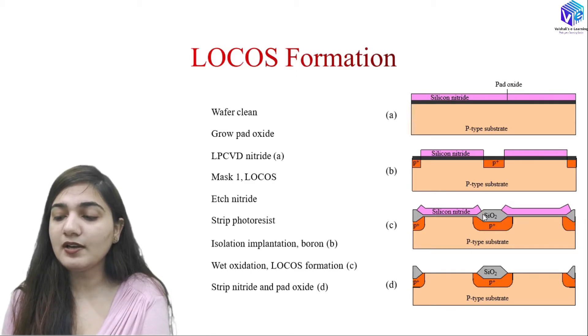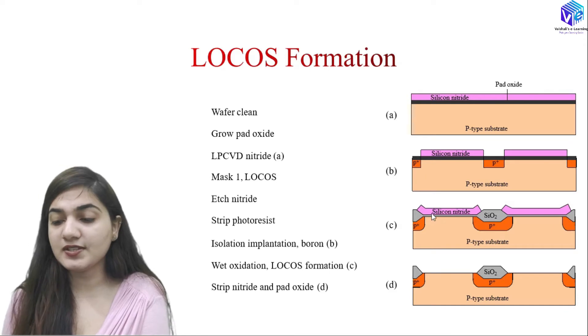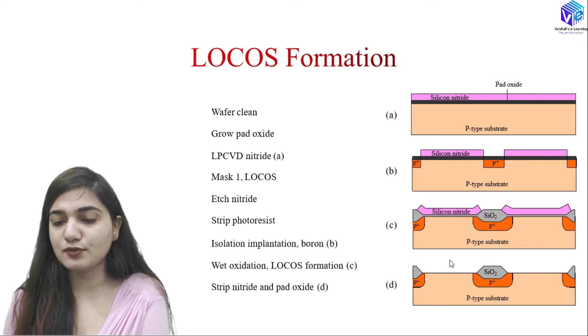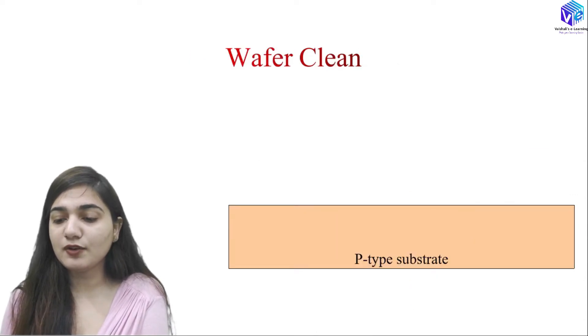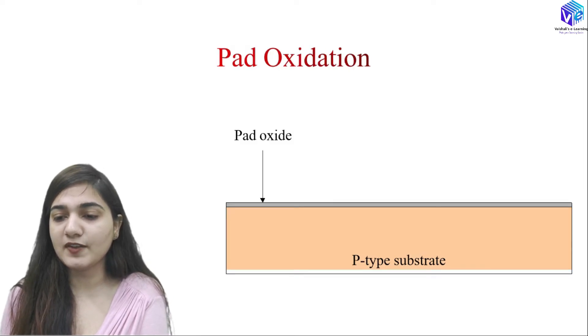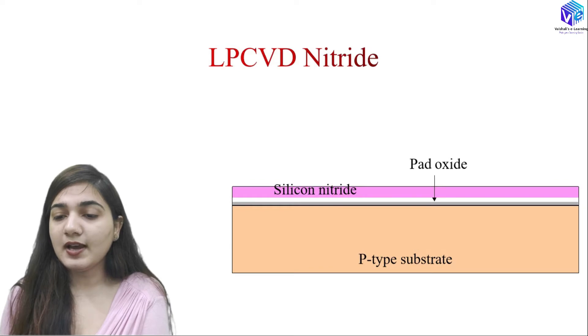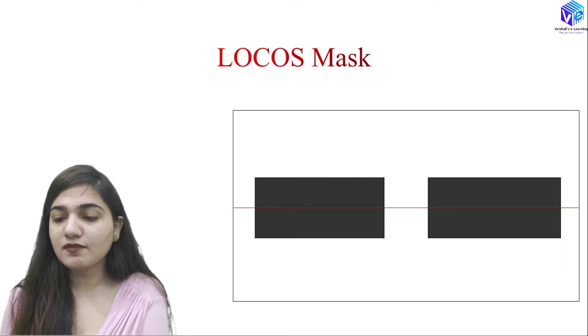After the isolation implantation, we perform wet oxidation to form the SiO₂ layer, which is called the LOCOS layer — this is the LOCOS formation. After that there is no need for the silicon nitride, so we remove the silicon nitride as well as the pad oxide. To summarize the LOCOS steps: clean the wafer with RCA cleaning, form the pad oxide layer, deposit LP-CVD silicon nitride on the pad oxide, then apply photoresist using the LOCOS mask.